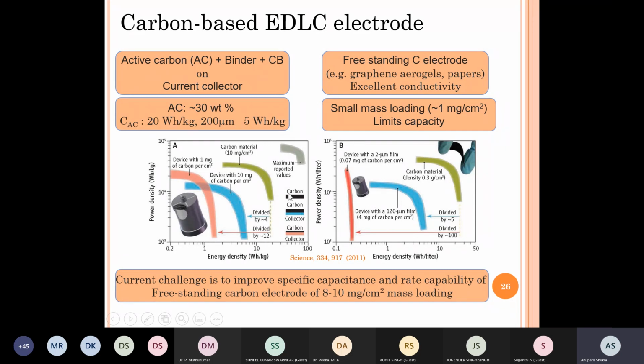So if you only have carbon, okay, then if you have carbon plus there is a current collector, and then carbon and collector, but the carbon is of a smaller thickness. Okay, so what is shown here is these are the values which you will find reported in research papers. This is only the active material values. This is Ragone plot again, presented flip side. So power density is on the y-axis and energy density is on the x-axis.